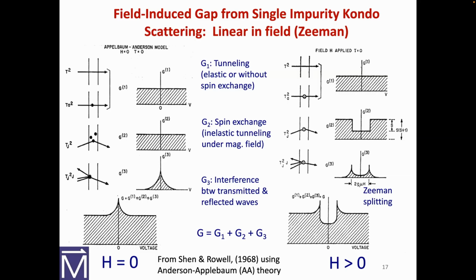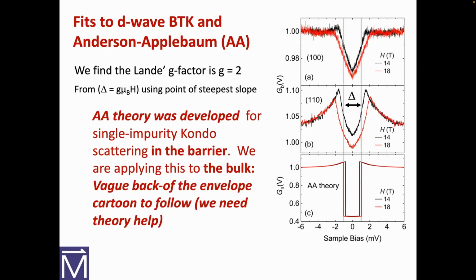Now, what I didn't go into, and I'll mention here, is that you also have something called a Kondo peak, which I won't go into, but it's like the third order effect. You can have an electron tunnel through, and you can have it superimpose with something that's Kondo scattering, and you can get this peak. But the important thing is that this thing grows linearly with applied magnetic field. And we fit it, and let's just talk about this.